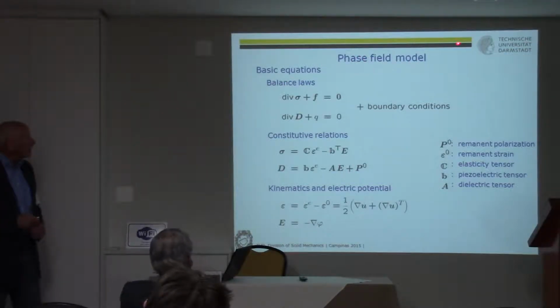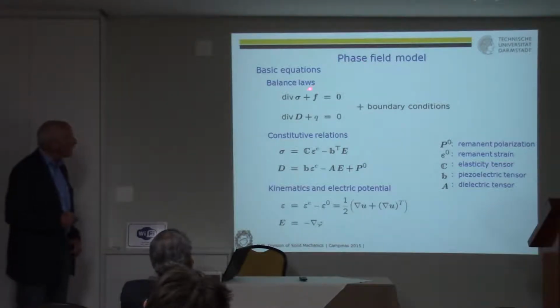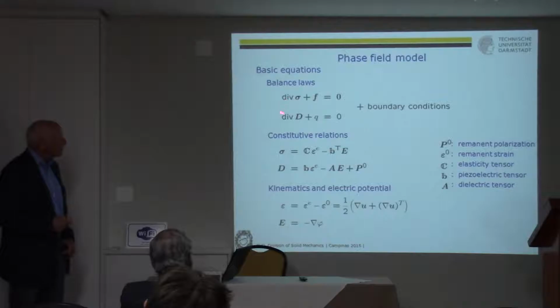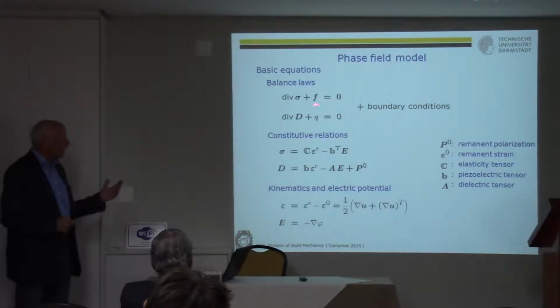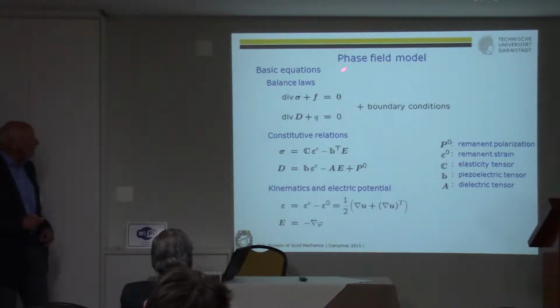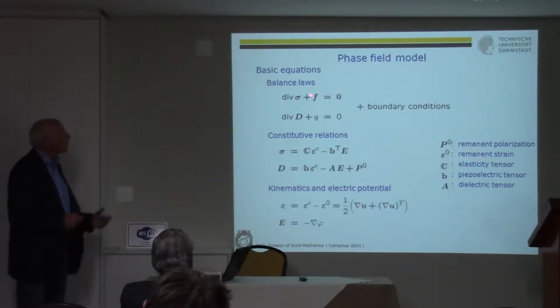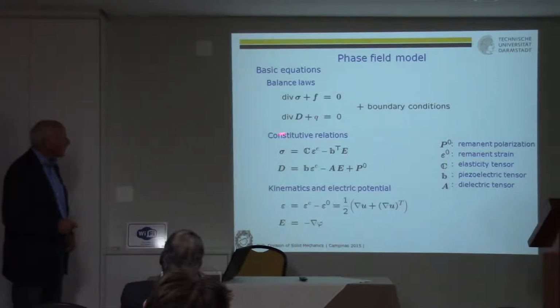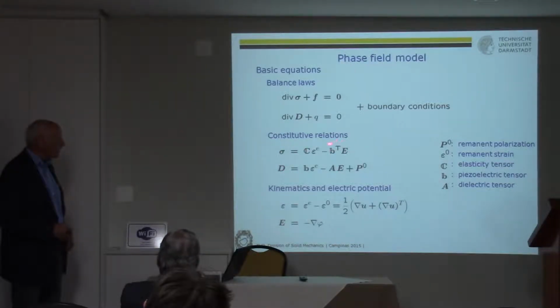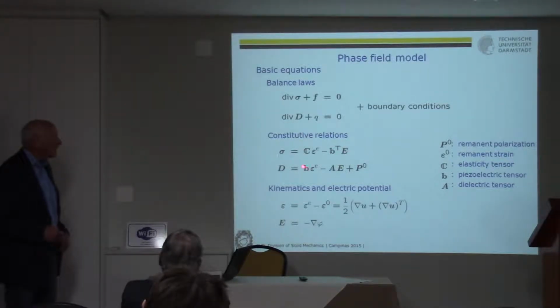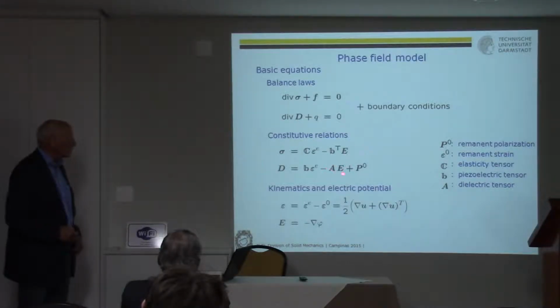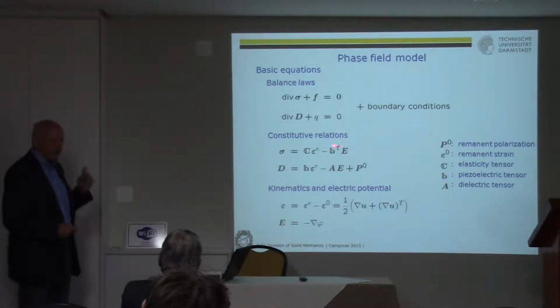Now, there are, of course, different methods to attack such a problem. In this case, we used the phase field model, and to explain it, it's very simple. Yeah, you start with the balance laws. Yeah, you have to take into account, of course, the coupling between the electrical and mechanical problem here, the mechanical equilibrium equation, the electrical equation, then the constitutive relation, and here you see the coupling. Yeah, here this part is the pure mechanical part. Yeah, and here the coupling between this B, the piezoelectric tensor, what also appears here is a dielectric tensor. So you have to know all these, say, material parameters, and this is one big problem.